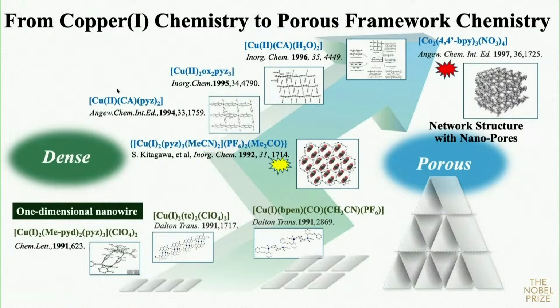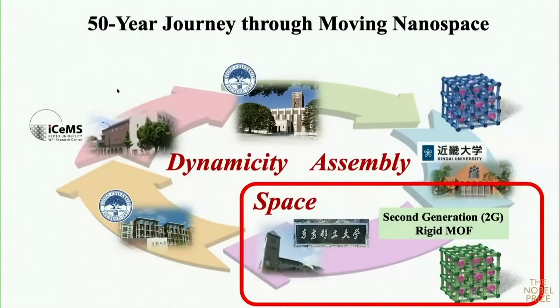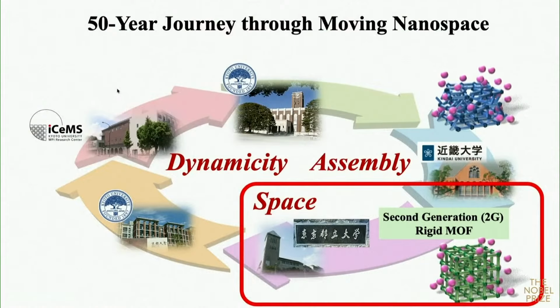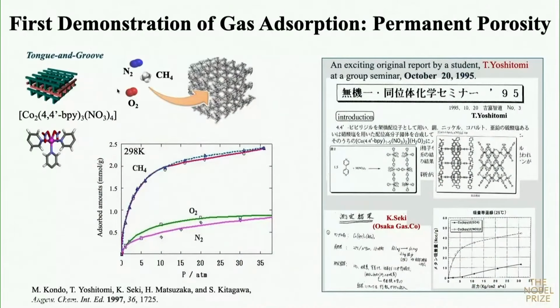This is the research timeline. At the beginning, we focused on densely packed structures, and after the event I told you about before in my slide, we focused on porous structures. So I moved to Tokyo Metropolitan University. Instead of copper(I), we used a cobalt-2+ ion to construct this kind of network structure. Without guest, this structure maintained the pore, so we carried out gas adsorption. We succeeded in this case.